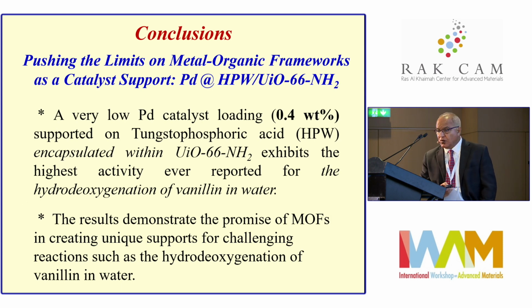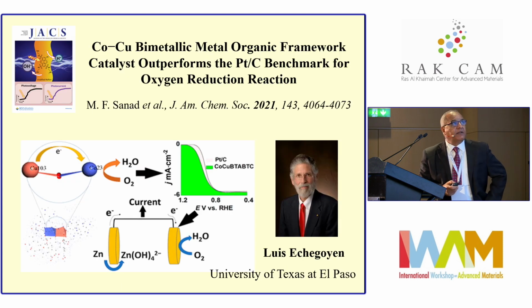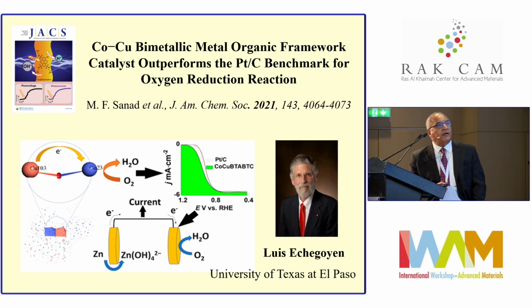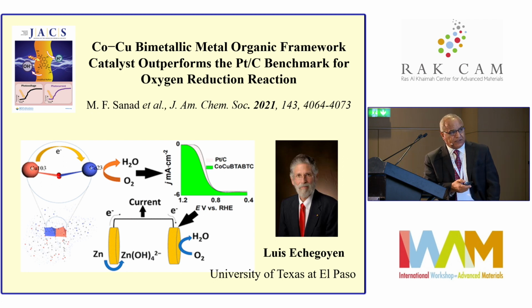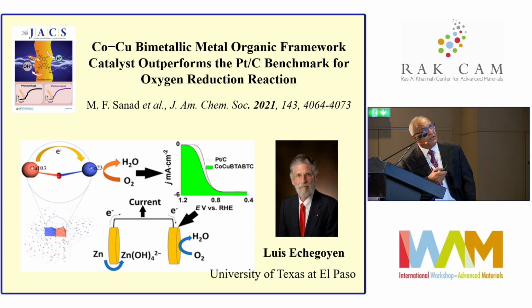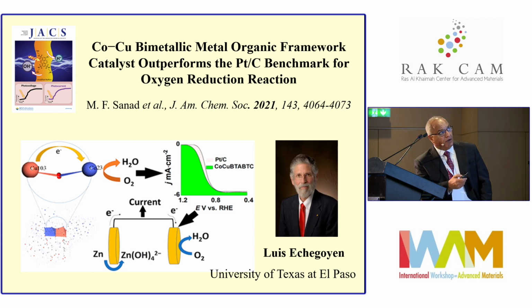So I go now to my next topic. This work is the formation of a cobalt-copper bimetallic MOF, which, as a catalyst, not as a catalyst support, we show can outperform the platinum carbon benchmark for oxygen reduction reaction. This work we did in collaboration with Luis Echegoyen from the University of Texas at El Paso, and I'll show you the results. We did the synthesis of the bimetallic MOF and the characterization in my lab, and in the Echegoyen group, they did all the electrocatalysis work reported in this paper.